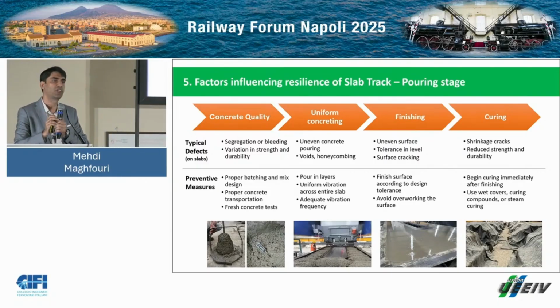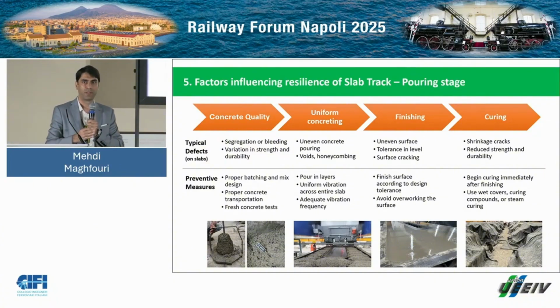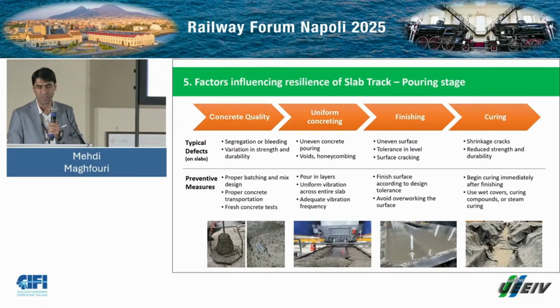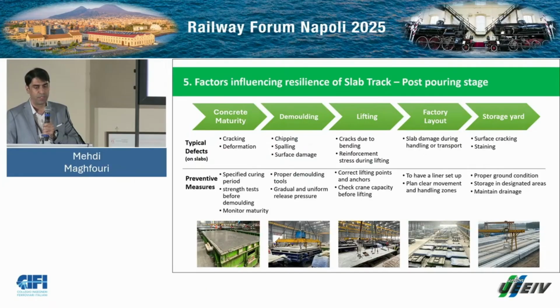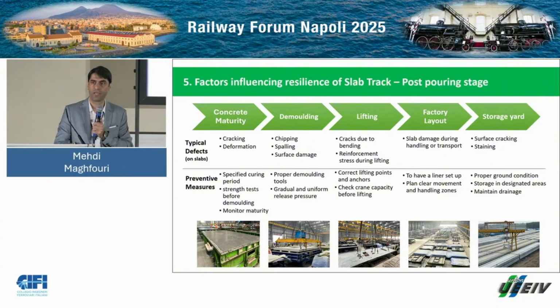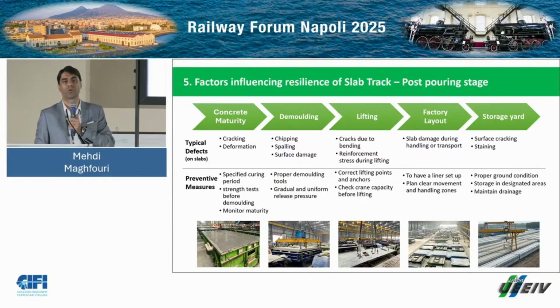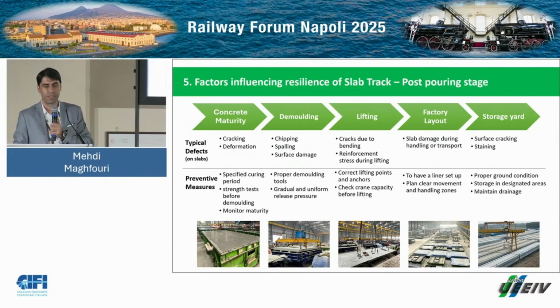Most of the defects actually come from the curing, because if there is no proper curing in place, we will have different types of cracks, like shrinkage cracks, plastic shrinkage cracks, and so on. So that's why the curing also shall be controlled. Concrete maturity: if concrete is not mature enough and we start doing the demolding, again, some defects like cracks or edge damage could happen to the slabs.